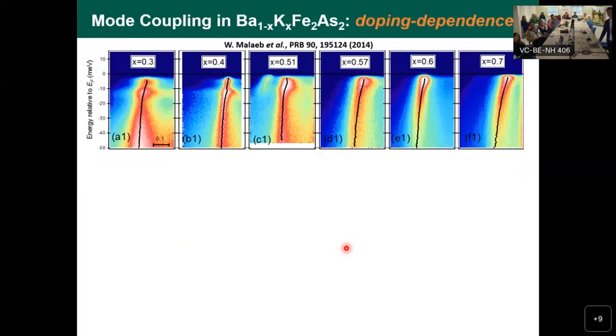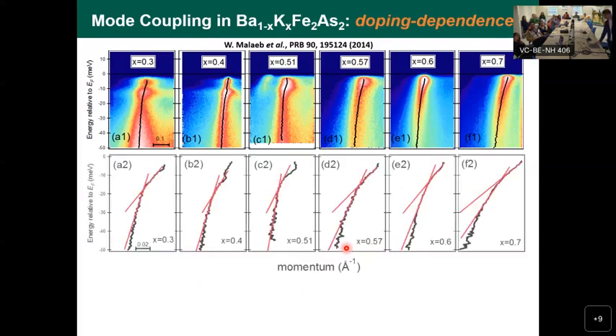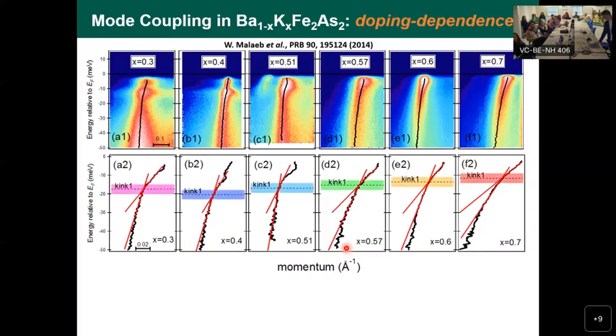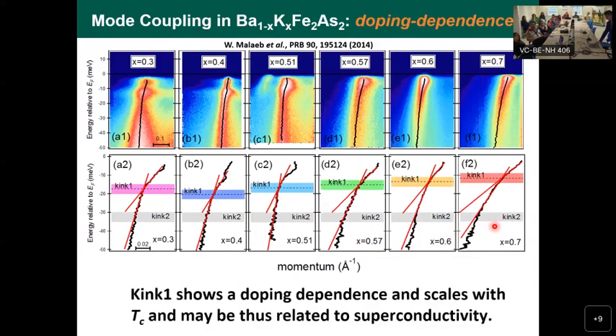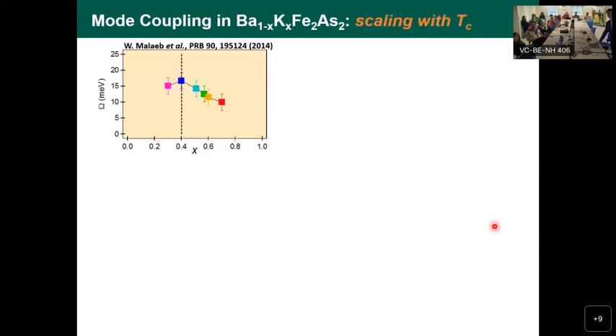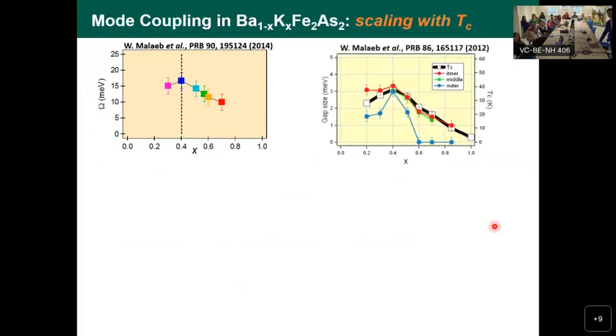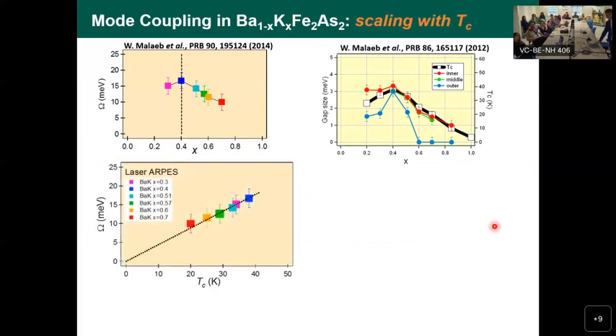And of course, we did a full study, various TCs and various energies for the kink. And we noticed something very interesting happening here. One energy scale is related to TC, is related to superconductivity. However, the other energy scale, which we call kink 2, is not related to superconductivity. You see the data maybe plotted in a better way here, relating this mode energy with the gap size. It showed a linear behavior and so on.